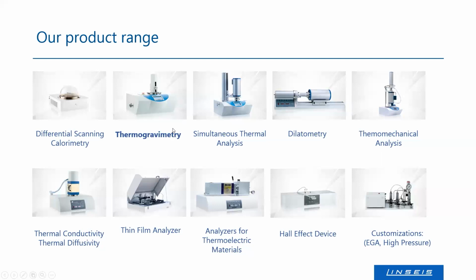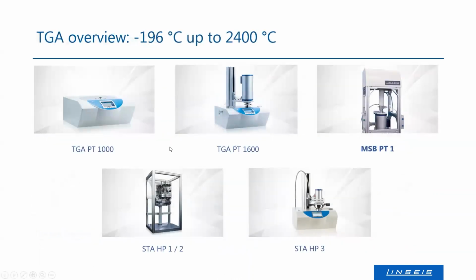And now coming back finally, today's topic is a very special form of thermogravimetric measurement, the so-called magnetic suspension balance. So therefore, I will enlarge our range or our product portfolio of thermobalances. There you can see we have the so-called TGA PT1000, which is the basic instrument with an integrated furnace that goes up to 1000 centigrades. And it is expanded to the TGA PT1600 platform. It's an instrument with a modular furnace where you can go up to 2400 centigrades by exchanging the standard furnace. The standard furnace is up to 1600. That's why it's called PT1600. And these two instruments are the typical tabletop thermobalances where you can measure thermal decomposition of any sample. You can evacuate it, you can flush it with any gas, measure under gas atmosphere, gas flow, whatever.